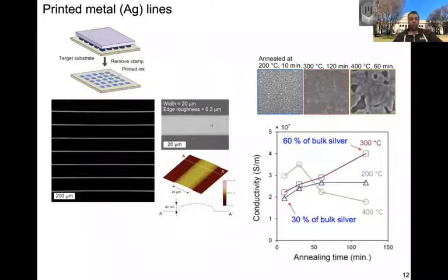So then a simple experiment in creating something that has basic functionality is to print an array of lines using a line stamp. And here's not the stamp, but an array of silver lines printed from a colloidal silver ink, a commercial ink, and then sintered. And if you do sintering in a furnace, you can optimize the time and temperature and get electrical properties here, just DC, simple stuff, about 60% that of bulk silver. It can go a little higher, not to full bulk silver, but interesting enough for printing devices.